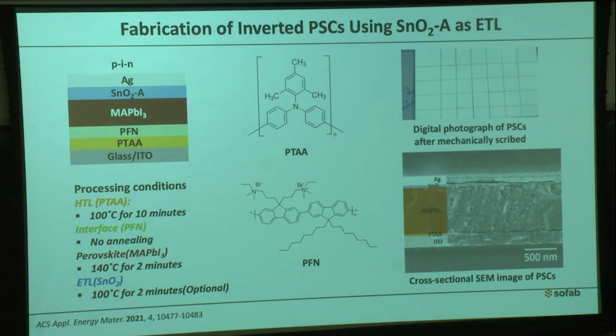Based on this result, we fabricated a perovskite solar cell. We deposited tin oxide directly on top of the perovskite. This is the digital photo of the solar cell we made. After that, we divided it into small pixels and measured the power conversion efficiency of each pixel.